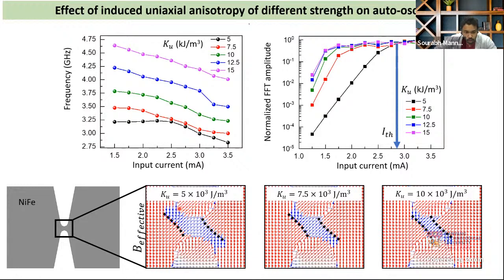The consequence is, once the auto oscillation starts by some input current, if we excite the magnet, if we pass some input current, then once the oscillation starts at these constriction edges, it is no longer confined around the constriction region. The spin waves generated from this auto oscillation get spread out around the constriction region. And because of this smaller confinement, it is much easier to disturb the magnetization to start the auto oscillation. And this explains why we achieve a lower threshold current once we start increasing the anisotropy energy.